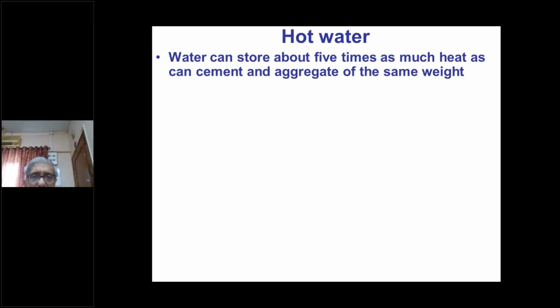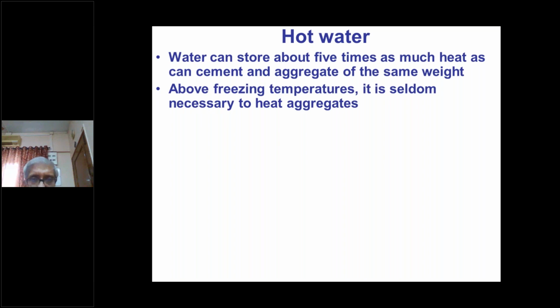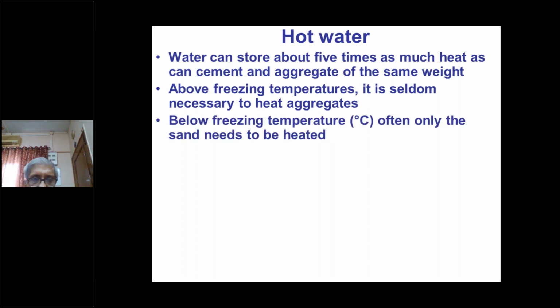Hot water can store 5 times as much heat as can cement and aggregates. Naturally, the specific heat is higher. Above freezing temperature it is seldom necessary to heat the aggregates. Below freezing temperature, often only the sand needs to be heated, which we did not do because we were doing just one experiment we did at 0 degrees centigrade with a foundation of 2 meter thick. So we were happy with the 10-degree temperature of the concrete, which we could achieve.